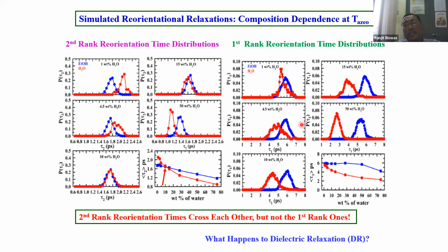And the first rank reorientation time we also calculated, because this can be probed in our laboratory itself through dielectric relaxation measurements. And what we saw here is that we did not see any overlap of these distributions, and they did not cross at any level, but that magical dependence on water concentration still continues for water. This means that the rotational diffusion is increasing even when the viscosity is increasing. So this is quite interesting.